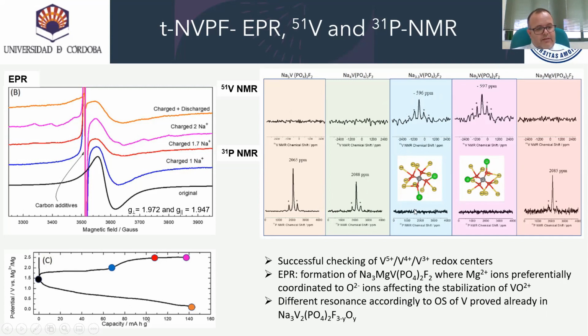In the original sample, this spectrum shows a dominant intense resonance signal at 2065 ppm, which suggests the presence of a unique 31 phosphorus local environment. Based on the Rietveld refinement and the visualization of the structure, the P1O4 and P2O4 tetrahedra lie in a symmetric environment in which each PO4 tetrahedron is connected with distorted VO4F2 octahedra. Each PO4 tetrahedron has in common the connection of, as we can see here, equatorial and axial VO4F2 distorted octahedra.